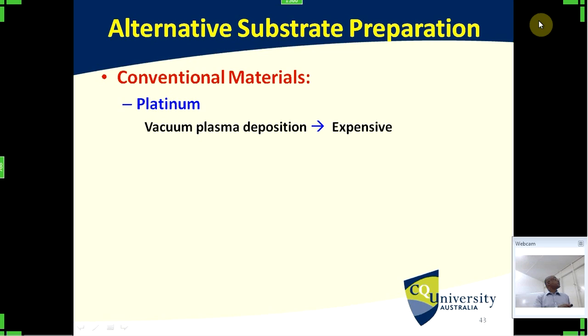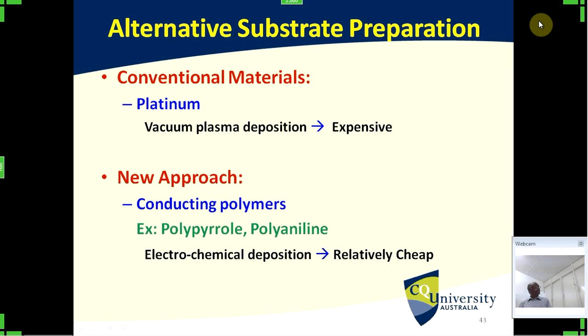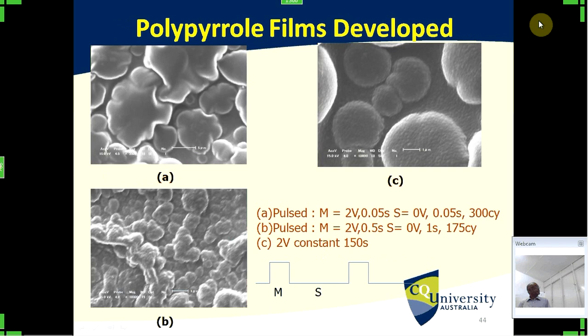So I thought of get rid of that one and using only chemical deposition method. So I use conventional methods. We use a lot of platinum, and I reduce the platinum usage and use conducting polymers and electrochemical deposition. These are the ones. What we did was I got the same electrochemical deposition system. Earlier what we did was let the current go for 90 seconds continuously, but this time we started pulsing it.